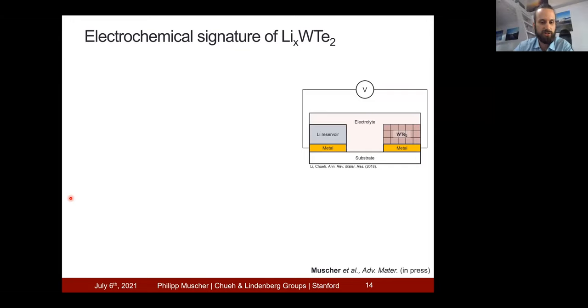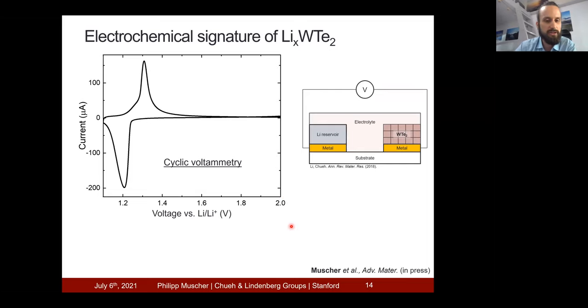Okay, so let's look at the electrochemical signature of tungsten ditelluride. And one way we can do this is called cyclic voltammetry. So here, what we are doing is we're applying a voltage between the lithium reservoir and our material. And we sweep this voltage. And at a certain threshold voltage, suddenly we measure large currents in our electrochemical cell. And these negative currents correspond to lithium and electrons moving from the lithium reservoir to our material. And then as we sweep the voltage back, we measure a positive current, which corresponds to the reverse reaction, lithium going out of our material again, back into the reservoir.